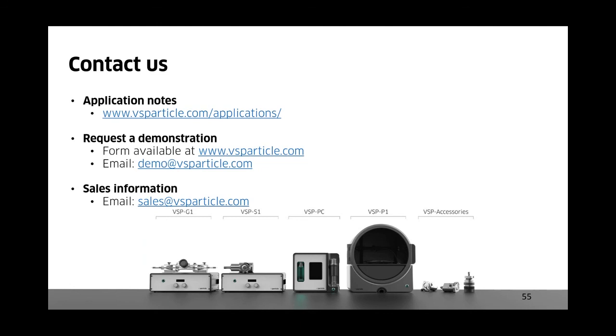How does the size of the electrode affect particle generation? Is the distance between the two electrodes maintained constant as it is consumed with time? In our reactor head, on one of the end caps, there is a little motor that moves one electrode closer to the other. So indeed, as you start ablating the electrodes, they'll get shorter, but this motor will ensure that the distance between the two electrodes remains constant. If you have particularly short electrodes, it will calibrate for that at the beginning, but there is a maximum size of the electrodes, around 2.5 centimeters.